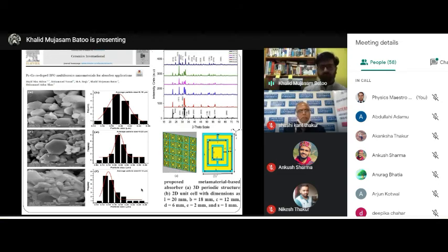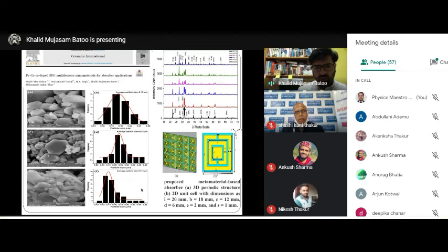In our study, we used bismuth ferrite, the BFO material, a multiferroic material with co-doping. You can see the SEM picture showing very clear crystals, though the size should not be calculated from SEM, it should be calculated from TEM. Here we did some calculation from SEM, showing 0.19 micrometer, 0.14 micrometer, and 0.23 micron for the three samples.